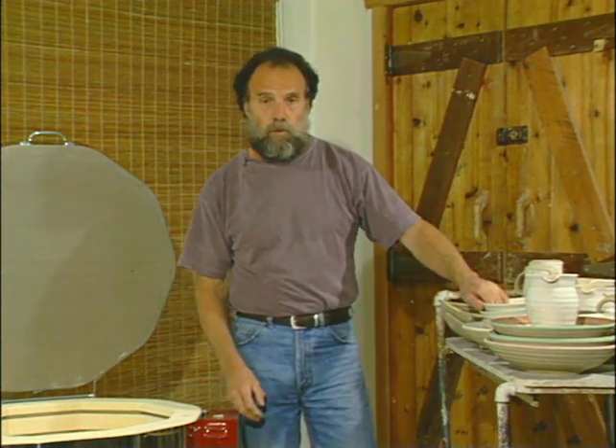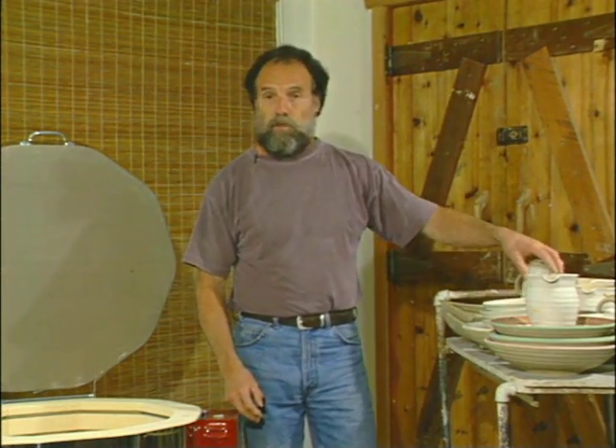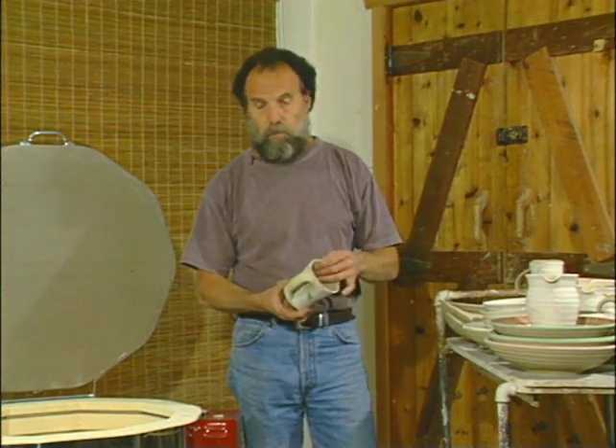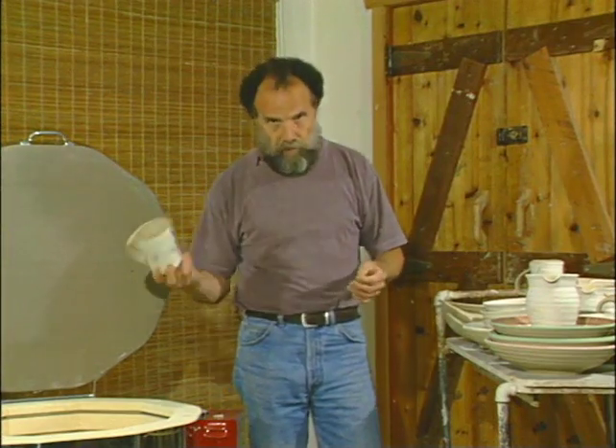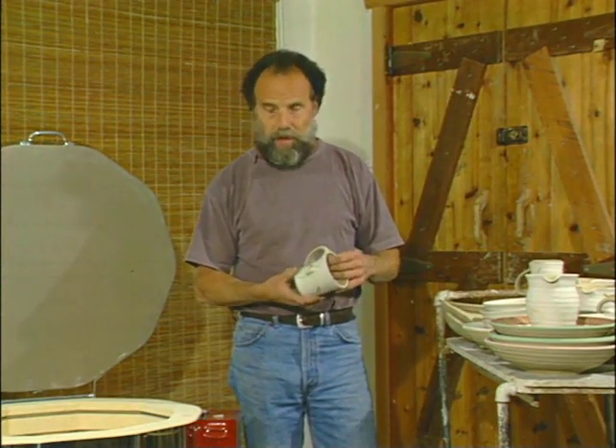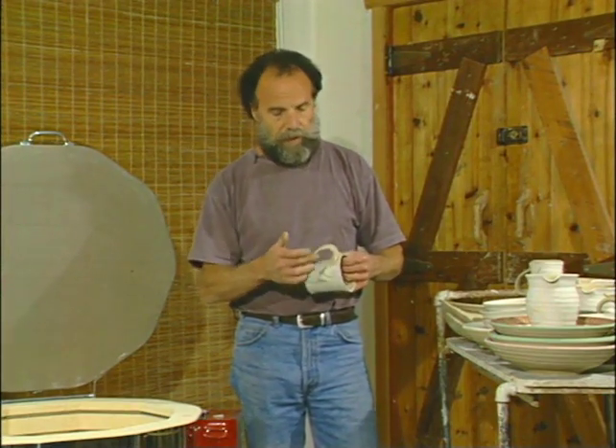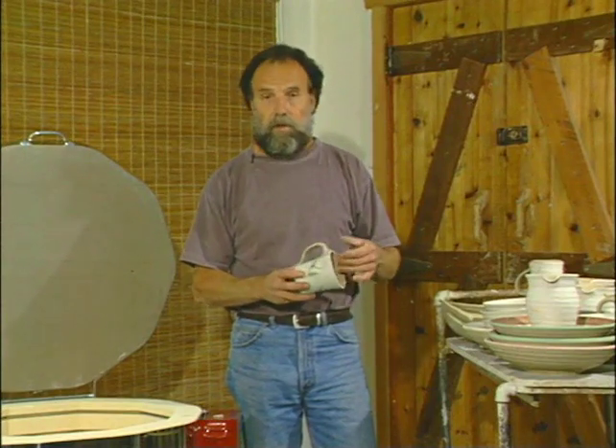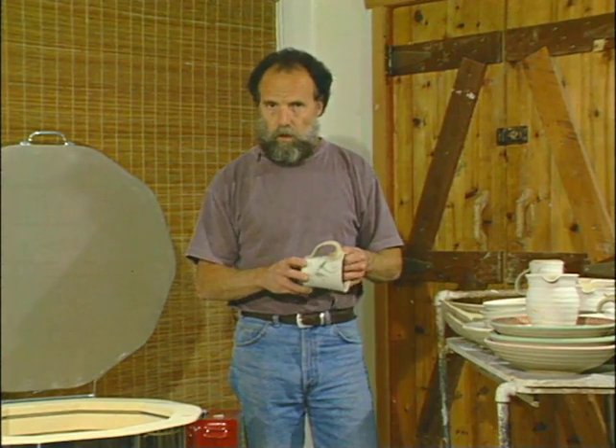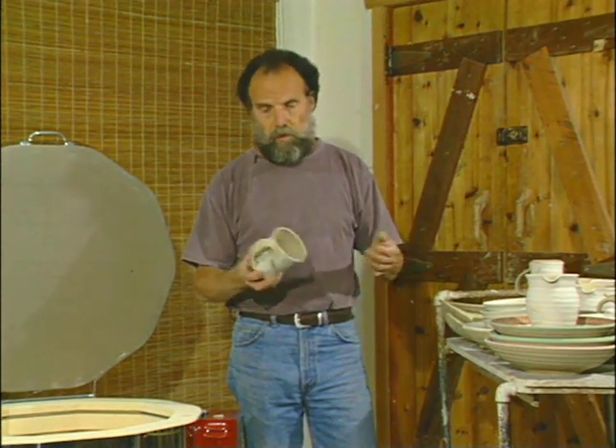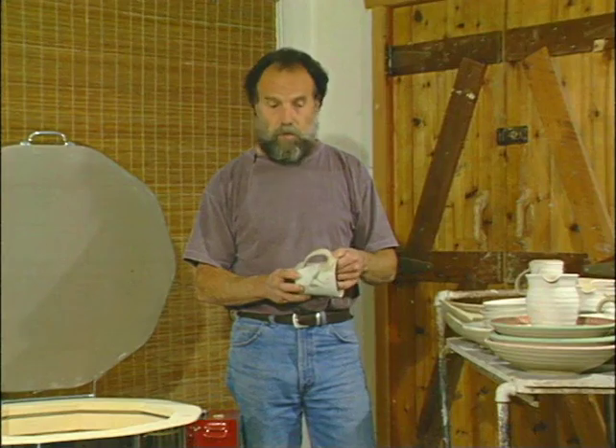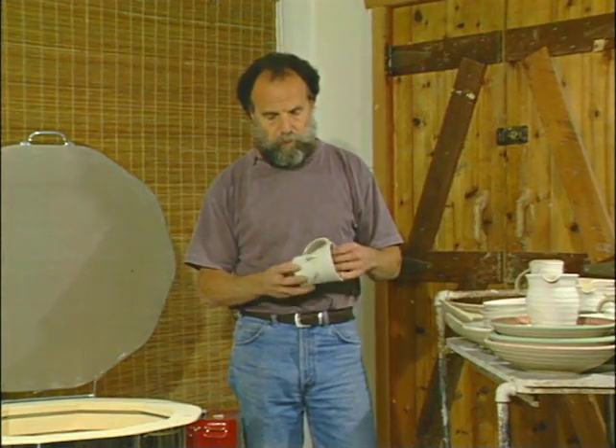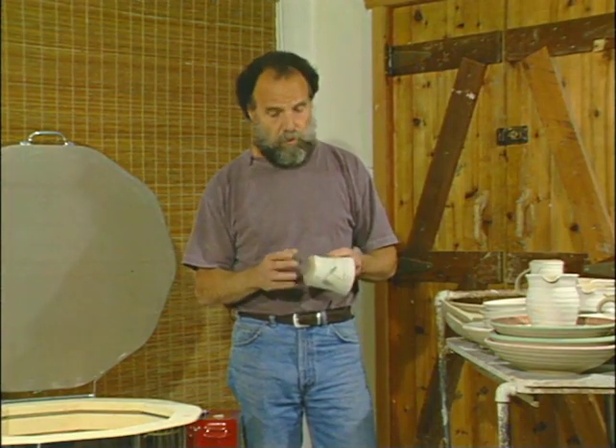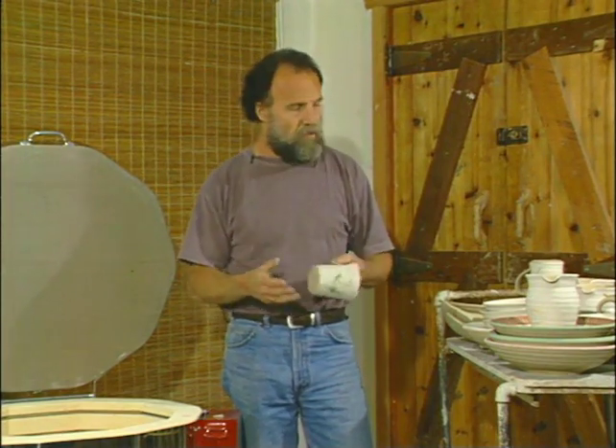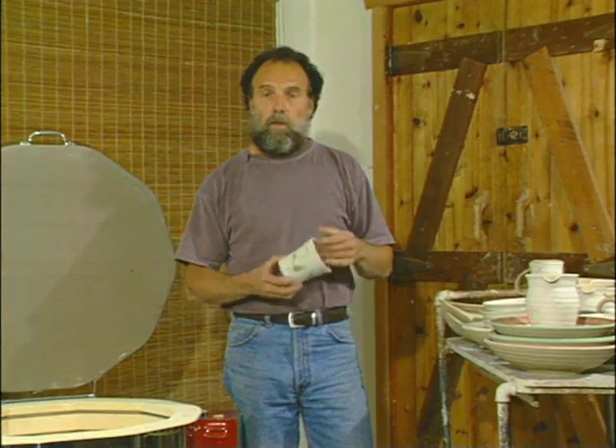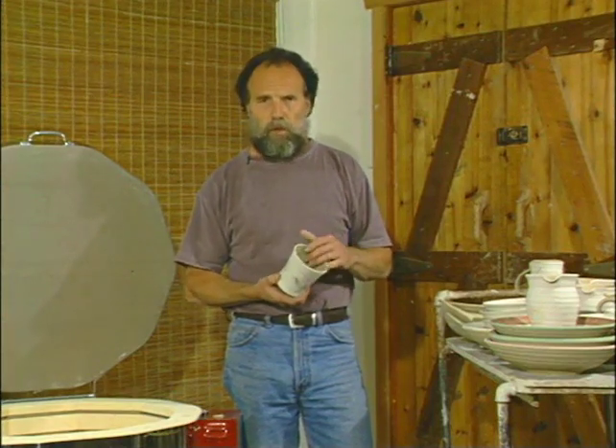It is possible to glaze pots without first bisquing them. For instance, we could take this pot and glaze it and then fire it in a glaze firing. The problem with that is that when you've got additions such as handles, spouts, knobs on lids, etc., the shock of dunking the pot into what is basically water and clay can be such sometimes that these additions will pop off. Again, this is also particularly important when you're dealing with some of the frail constructions that children make. So the reason that we're bisquing is to make the pots more durable for glazing.